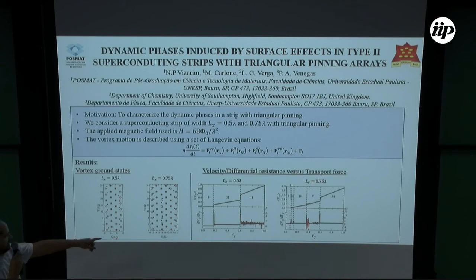The vortex motion is described using a set of Langevin equations, where we have the vortex-vortex interaction, the vortex interacting with the shielding screening of the surface, the vortex interaction with the current, the vortex interaction with the pinning sites, and the vortex interaction with the self-images outside of the sample. We obtain the vortex ground states using the simulated annealing technique. We can see that vortices are pushed towards the center of the sample through the surface effects, and this induces different dynamic phases. We can see here in the velocity against transport force, and also the derivative of velocity against the transport force, the three phases when the width is 0.5 lambda, and when the width is larger, 0.75 lambda, we have 6 dynamic phases. We're open to suggestions. We intend to do more calculations with different widths. Thank you. Come to my poster 18.